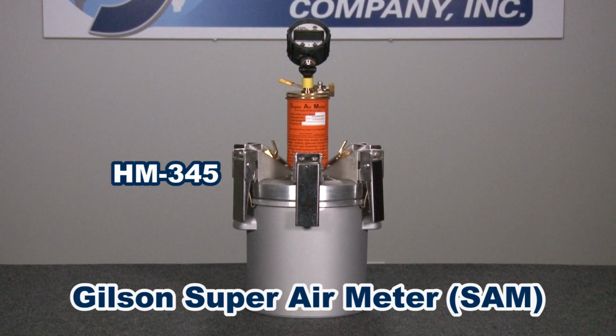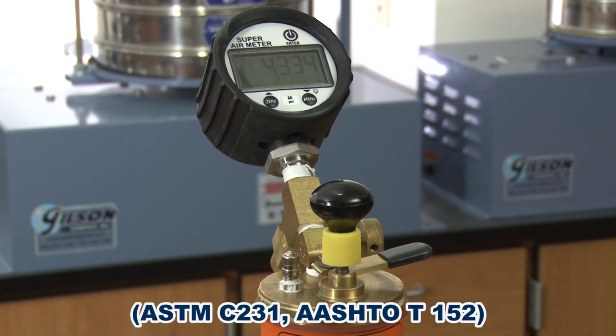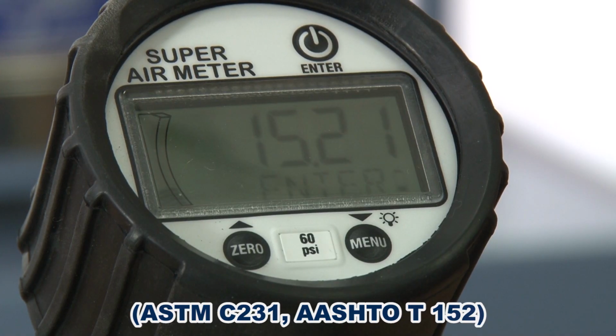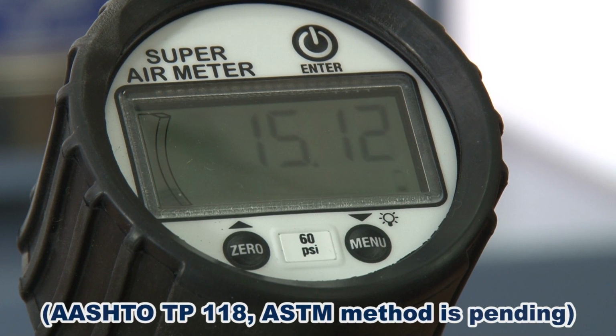The Super Air Meter, or SAM, is a modified Type B concrete air meter that determines air content and also characterizes the size and distribution of air bubbles within the concrete mix. The SAM meter allows accurate predictions of freeze-thaw durability of exposed concrete. The initial air content part of this method meets test specification requirements. The complete SAM method is detailed in AASHTO TP118.